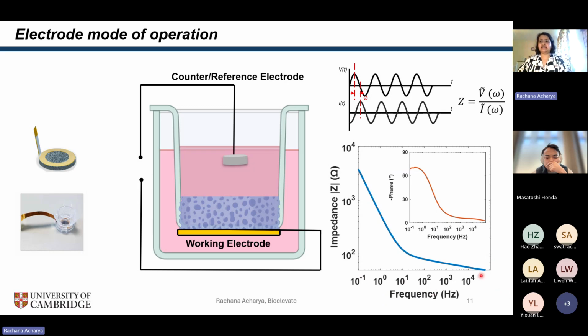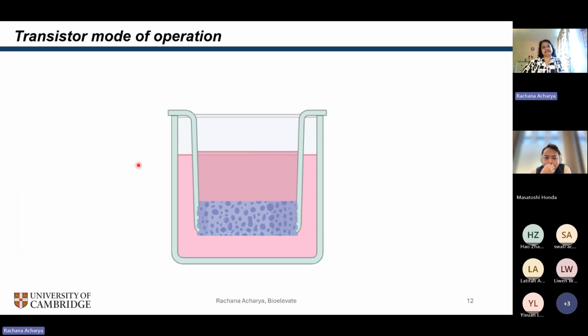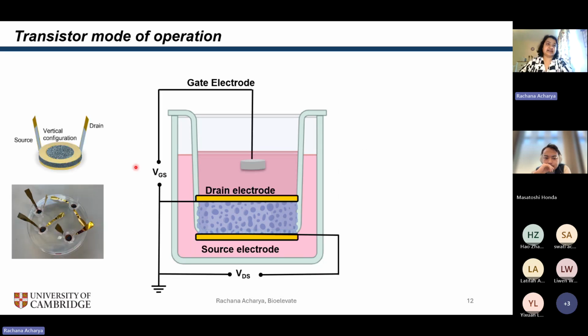So what you can see is that at high frequencies, you have this kind of plateau in the impedance, because your system is mostly acting as a resistor. And at low frequencies, you see more of a capacitive behavior of the scaffold plus this gold electrode, and that's why you have this linearly changing impedance. So this is our baseline measurement for the scaffold integrated into an electrode mode. What I can also do is, instead of connecting one gold electrode, connect two gold electrodes, and the electrode on top can function as my gate electrode, and I can turn this device into an OECT, or an organic electrochemical transistor, because now I have three terminals.